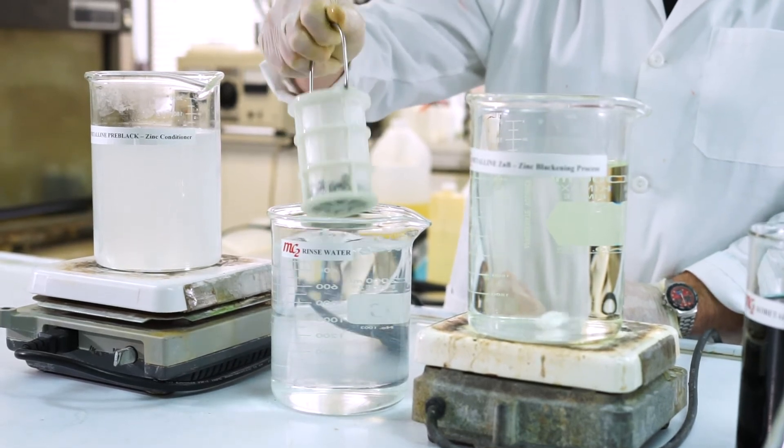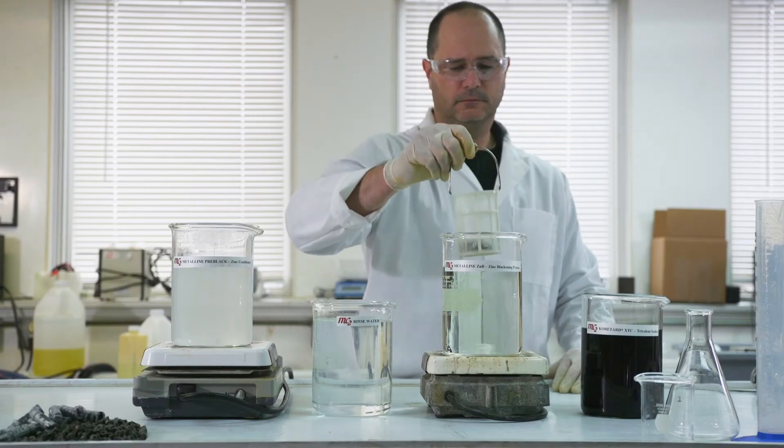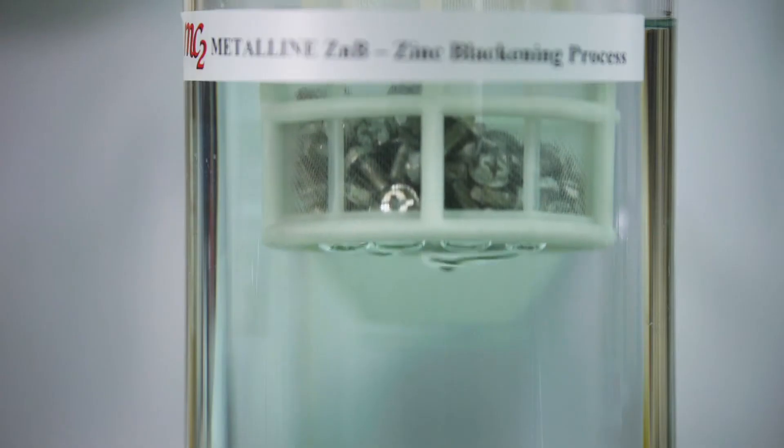After thoroughly rinsing to minimize contamination, parts are immersed in the Metalline ZnB blackening solution for 1 to 3 minutes.